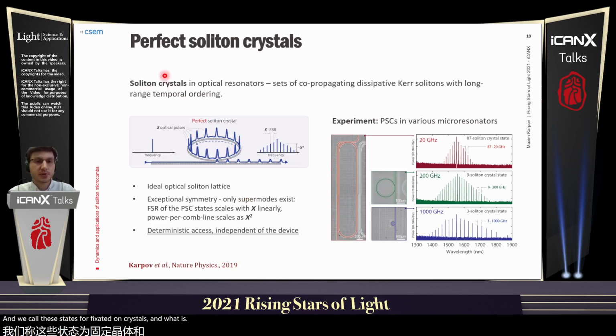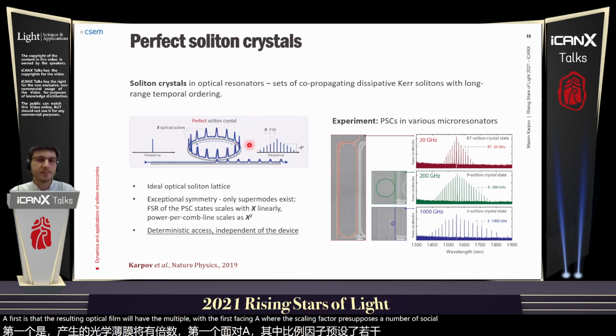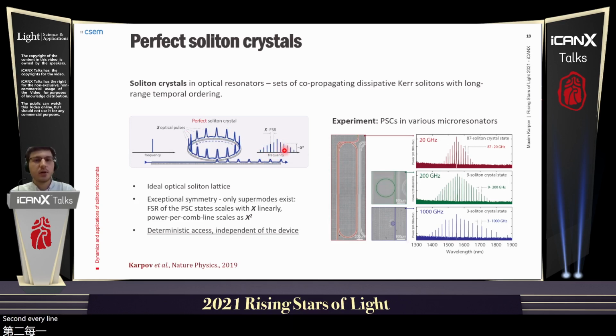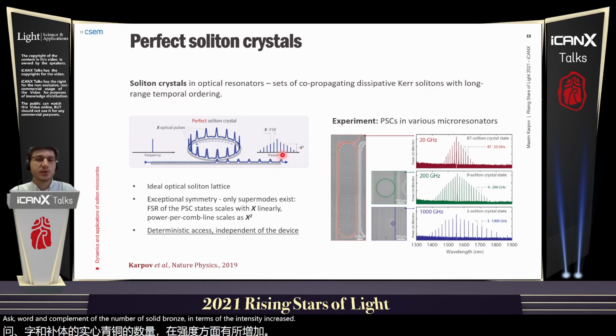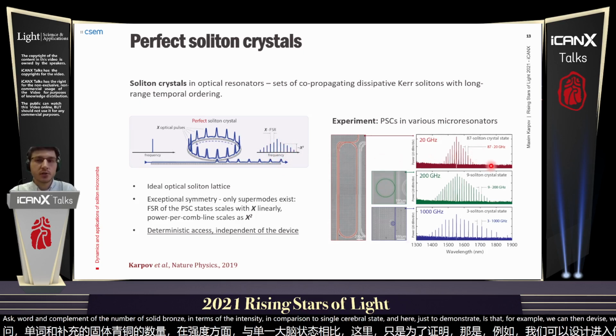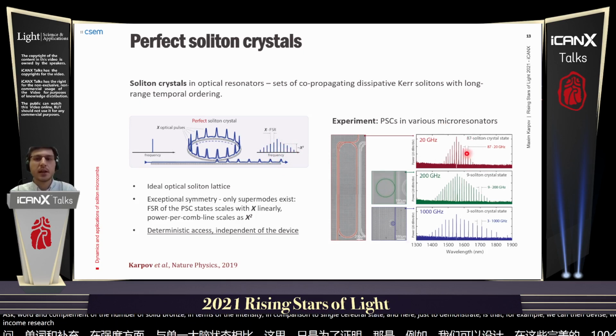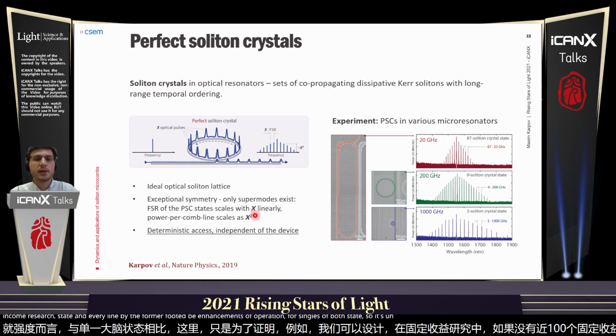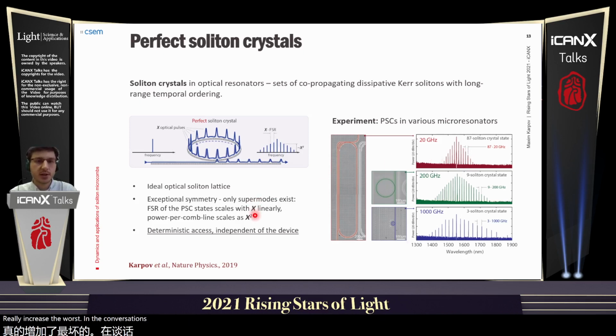And what is cool about these perfect soliton crystals? Well, several things. First, the resulting optical comb will have a multiple FSR spacing, where the scaling factor corresponds to the number of solitons inside the cavity. Second, every line of the resulting comb will get an enhancement, squared in the number of solitons, in terms of intensity in comparison to a single soliton state. Just to demonstrate, we had a device where we got almost 100 solitons in this perfect soliton crystal state, and every line got almost 40 dB enhancement in comparison to a single soliton state. So it's a real boost in the conversion efficiency of these soliton states.